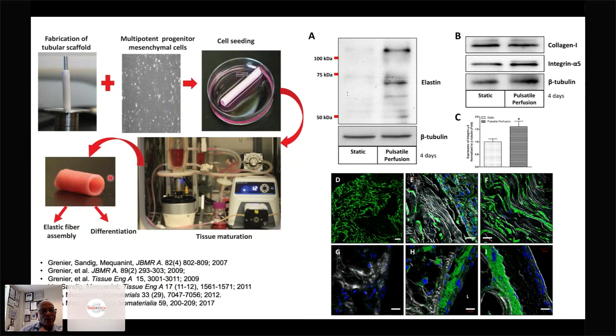So we have fabricated scaffolds, seeded vascular cells or multipotent progenitor mesenchymal cells, and put them into a bioreactor. We mature it for a period of time, and we have been publishing in this field since 2007, and we really have found some interesting things. The polyurethane biomaterials actually served as an excellent model biomaterial. Polyurethanes can be designed to be biodegradable, but the ones that we have used are biostable, because when we did our signaling studies, we don't want any degradation products to confound our data interpretation.